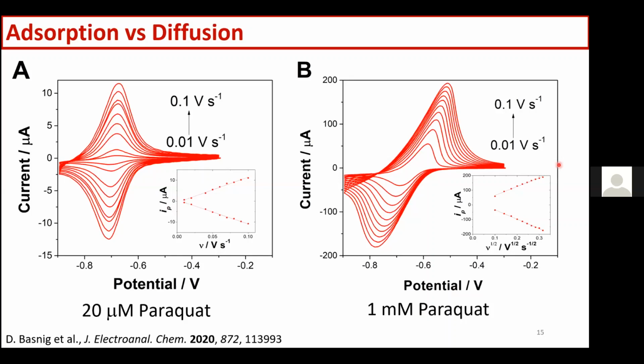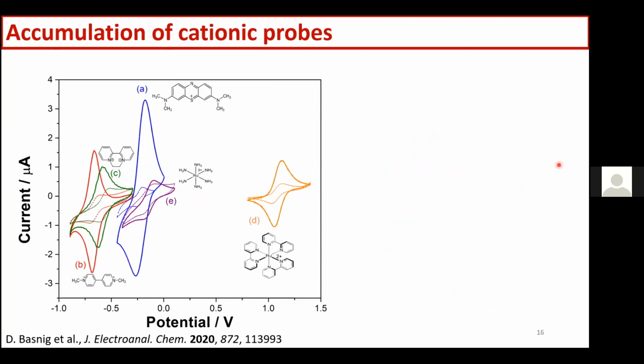So we tried this accumulation for different types of probes. I showed you paraquat here in red. We tried diquat, which is here in green, methylene blue, and then ruthenium hexamine, and then ruthenium trisbipyridine. The solid lines are the signal after 50 cycles at the modified electrode, and the dashed signal is the signal after 50 cycles at the bare electrode.